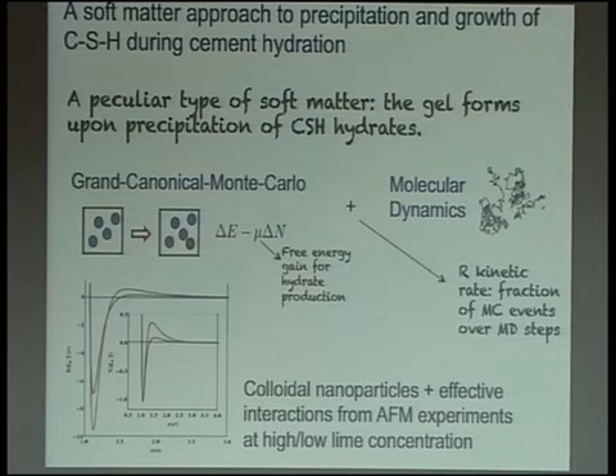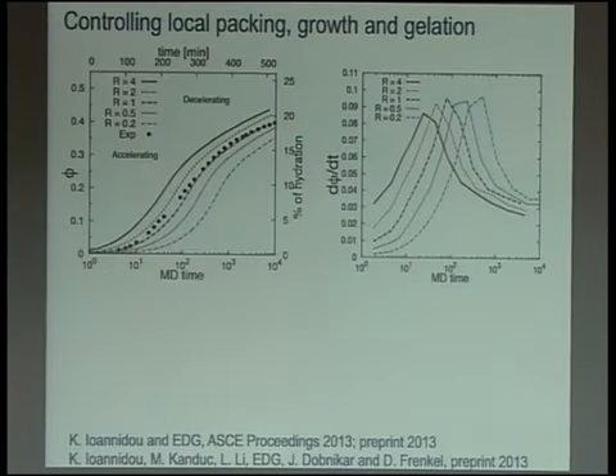And we are able to actually monitor the densification of the gel as particles precipitate and start to form the gel. We can actually reproduce this acceleration and deceleration that is seen in the experiments. We can try to compare several aspects of the gelation in the experiments, and we do see that the gel